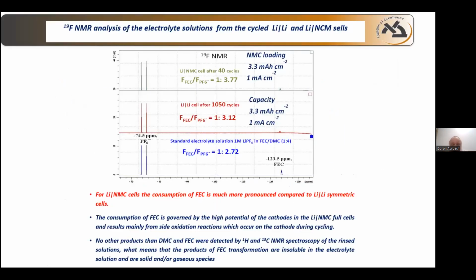So what is interesting is the surface chemistry and the unique chemistry that we develop. And I show you here results from measurements of the electrolyte solutions before and after cycling. Now we have in our systems two sources of fluoride. We have fluoride in the fluorinated co-solvent, and in the lithium hexafluorophosphate, the salt anion. So we have initially a ratio between the fluoride of the solvent and the fluoride of the salt, and we measure it by fluorine-19 NMR.